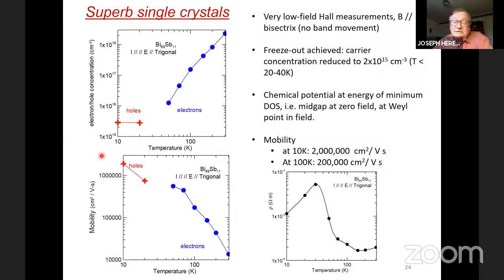So these samples have the chemical potentials really at the Weyl points. Well, in this, they are semiconductors. So here the chemical potential is in the gap. And when they flip in the quantum limit to being Weyl semimetals, the chemical potential comes at the Weyl points. We also have made other samples with very low mobility, 20,000 mobility, to contrast and to be able to quantify the effect of defect scattering on our measurements. But these are the good samples.